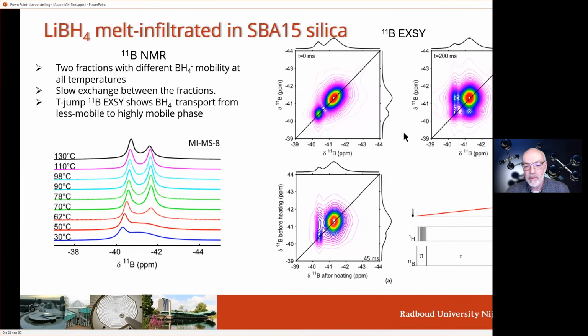And that means that BH4 units go from this highly mobile phase to the more rigid phase and vice versa. And the most exciting experiment we did is where we cranked up the temperature in this time between the periods where we connect the chemical shift to each other, and then we see it becomes asymmetric. And this tells us that one phase grows at the expense of the other phase. So actually going to a higher temperature, we see that we get more of this mobile phase, and that there is exchange of the different ions between these phases.